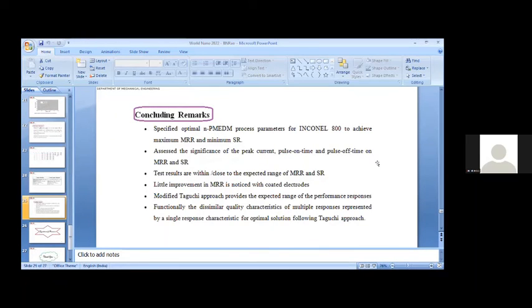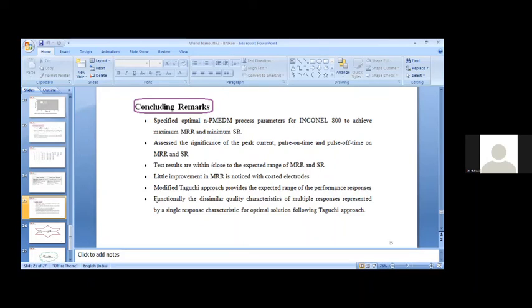So when I come back to the conclusions, we have specified optimal nanoparticle mixed EDM process parameters for Inconel 800 to achieve maximum material removal rate and minimum surface roughness. We assessed the significance of the peak current, pulse on time, and pulse off time by performing analysis of variance. Test results are within or close to the expected range of MRR and SR. Little improvement in MRR is noticed with coated electrodes. The modified Taguchi approach, whatever I have explained, provides the expected range of performance responses. As you know, when you repeat the experiment, you will not get the same number. There will be some variation that we can capture. Then, the dissimilar quality characteristics of multiple responses are represented by a single response characteristic for the optimum solution, following the Taguchi approach. So these are my concluding remarks.